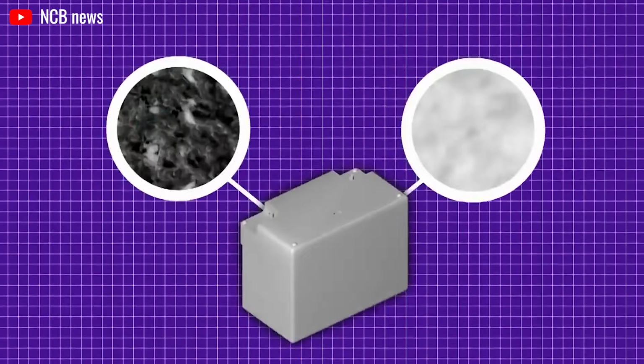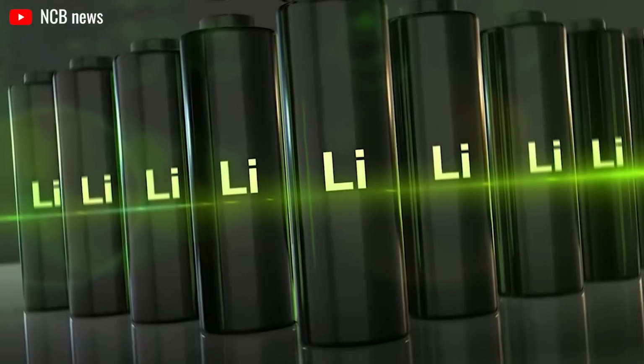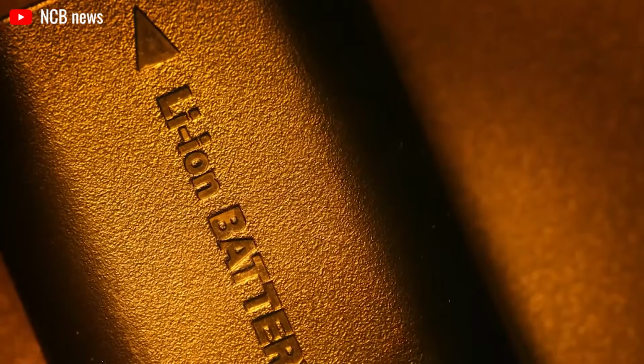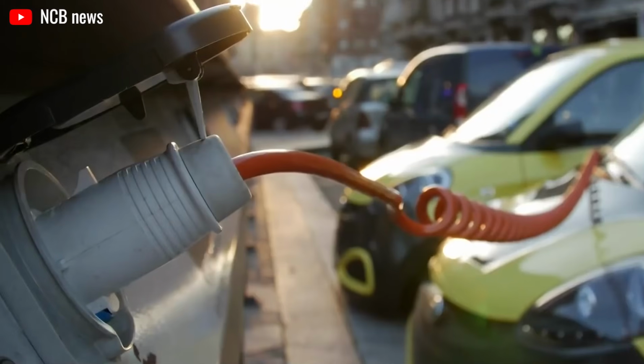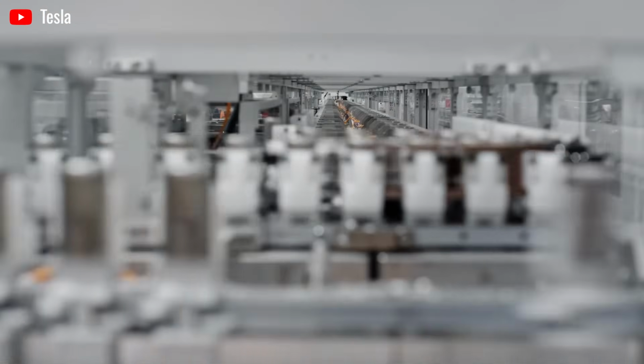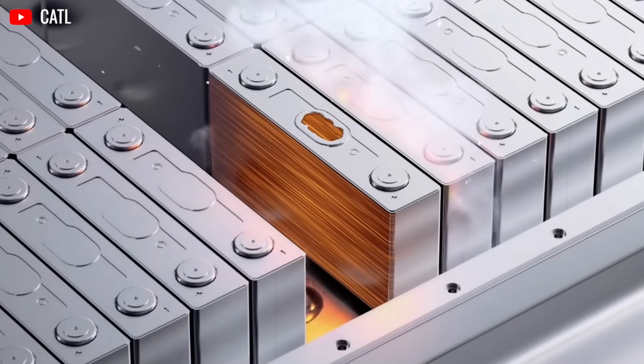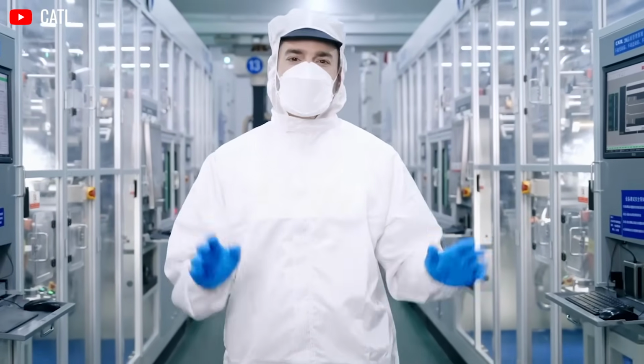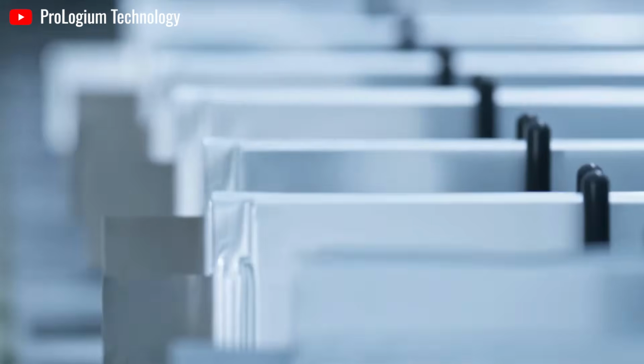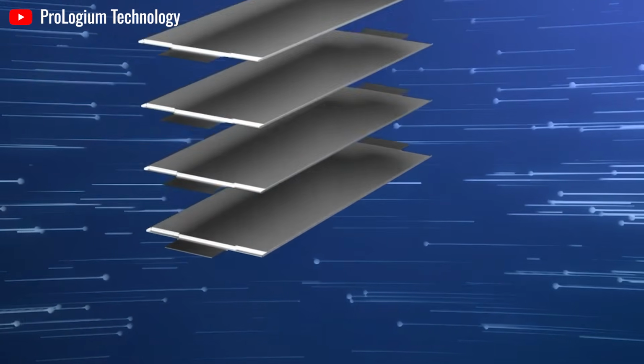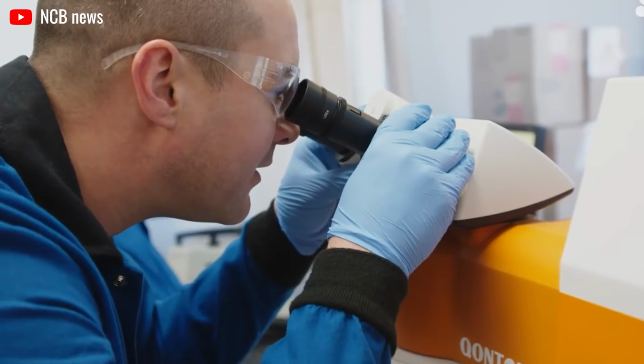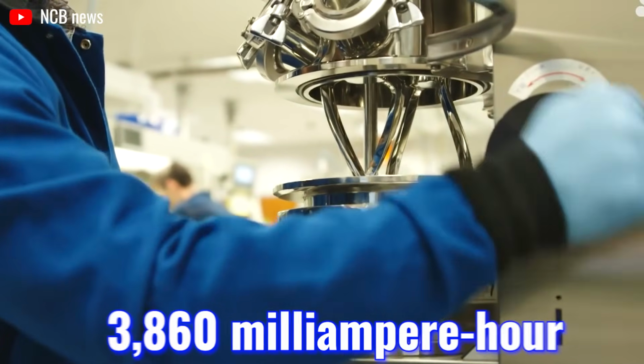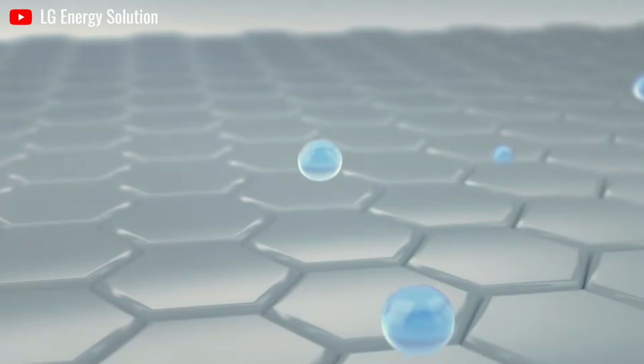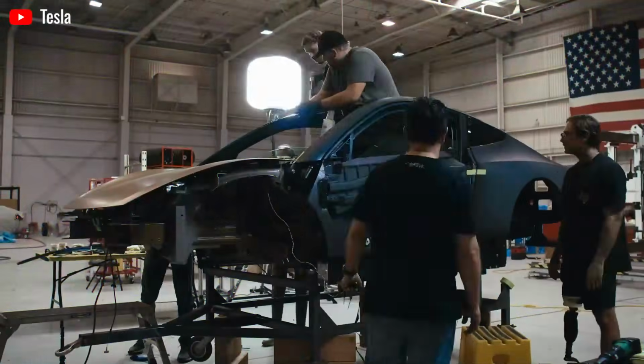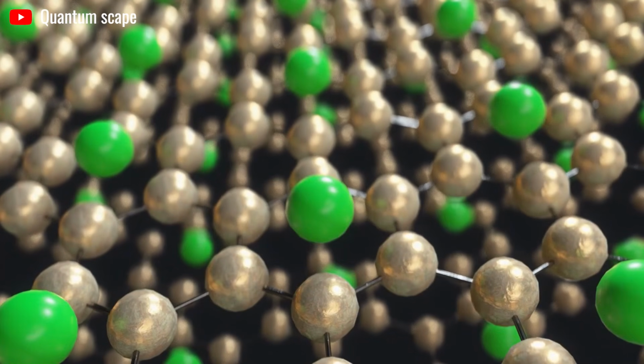in real cells. Consider lithium dendrites, the needle-like metal structures that form when lithium plates unevenly during charging, at moderate current densities. Modern graphite anodes manage this risk reasonably well, but at energy densities approaching 400 watt-hour per kilogram, lithium metal becomes almost unavoidable, because graphite simply cannot store enough lithium per gram. Lithium metal has a theoretical capacity of 3,860 mAh, nearly 10 times that of graphite. Sounds perfect, right? The problem is that lithium metal is chemically aggressive and mechanically unstable.